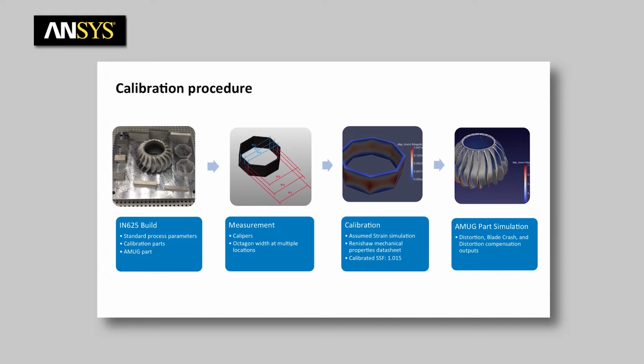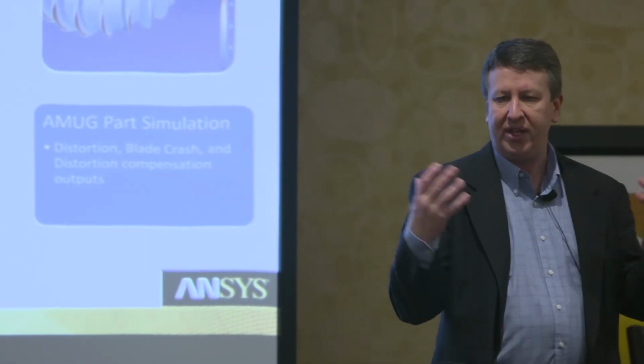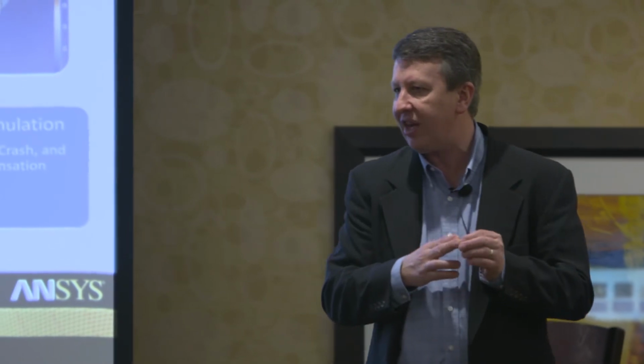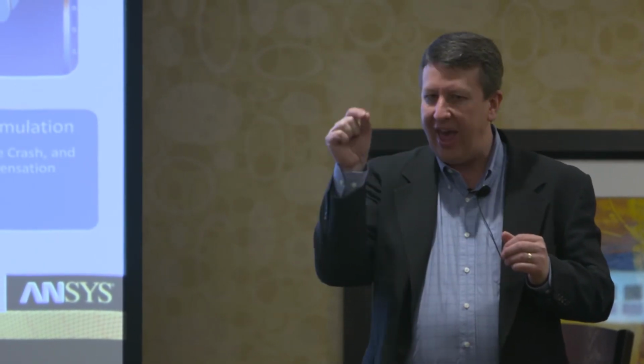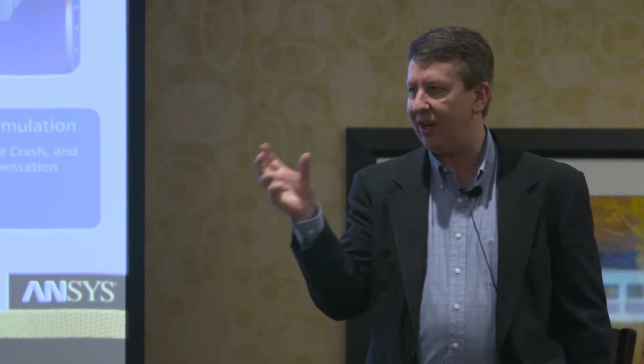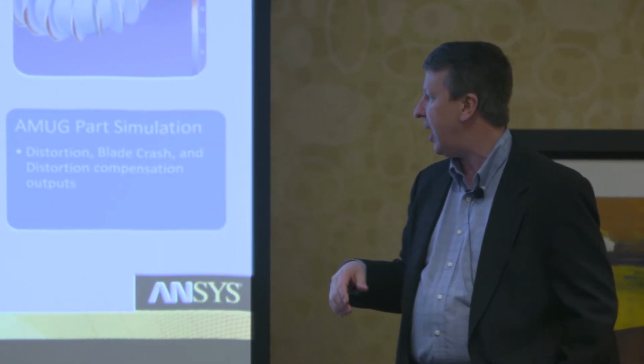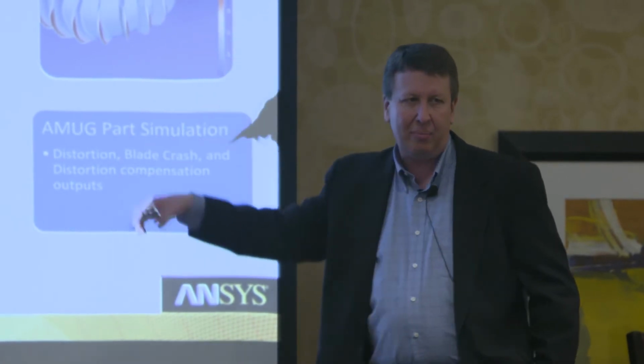And then the third thing we did was calibrate what we call a strain scaling factor. So in this most simple simulation we did, we are accumulating the average amount of strain everywhere. So all we're doing right here is, with a single measurement, saying what's the average strain that occurred in this part? And now we say, if that average strain occurred in the complex part, what would happen there? That's really this simple test. And it's our most simple, fastest simulation type. And then we went and predicted this complex part with that simple simulation assumption.